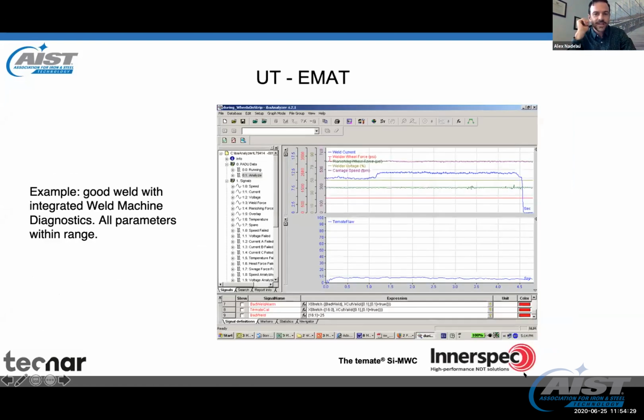So here is actually software from Innerspec, and the upper chart is the welding parameters. We can see actually a change in the welding current, and the lower chart is the backscattered sound in percentage. So in this case, it's a good weld. There was no strong backscatter whatsoever, so it's a weld that's ready to go through.